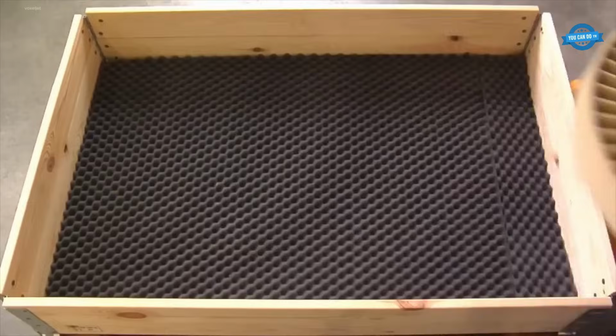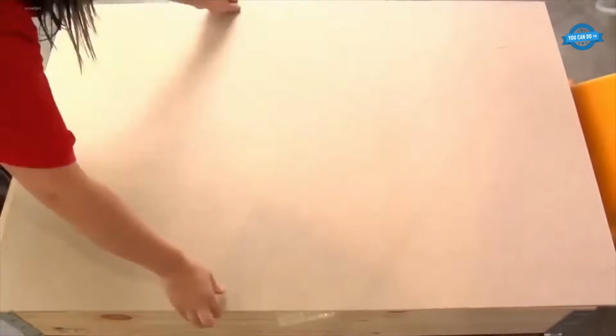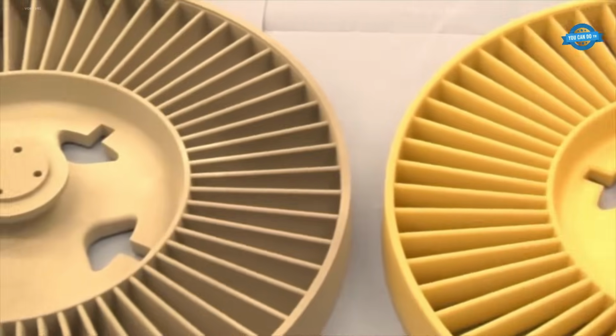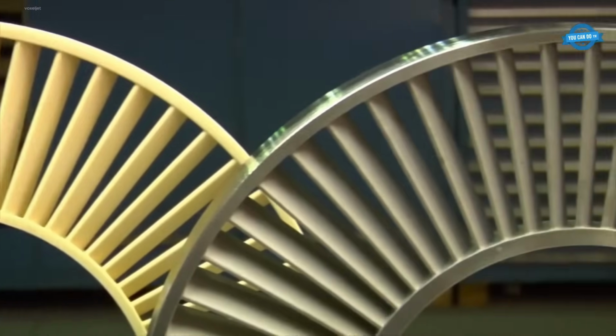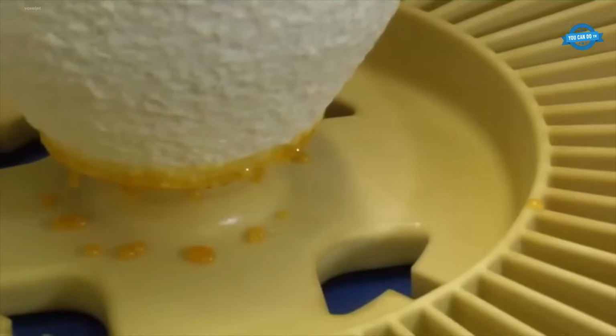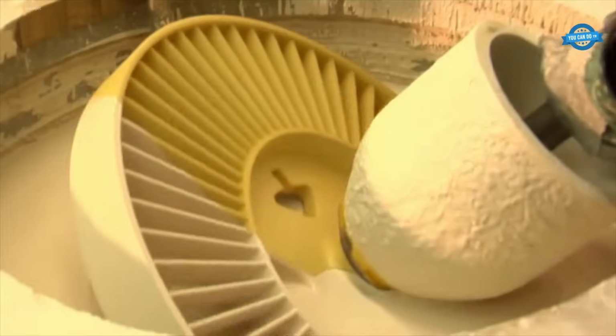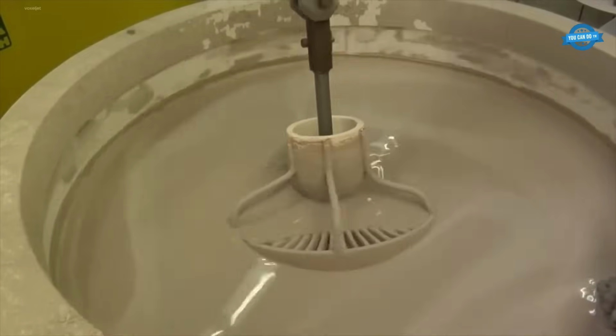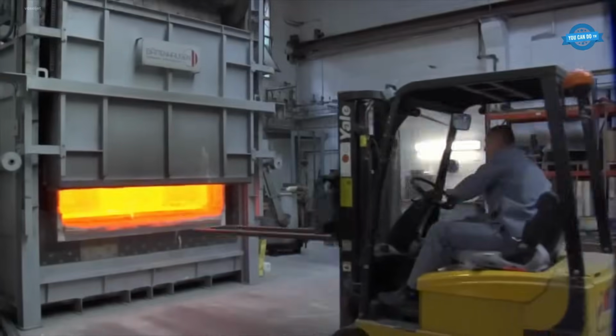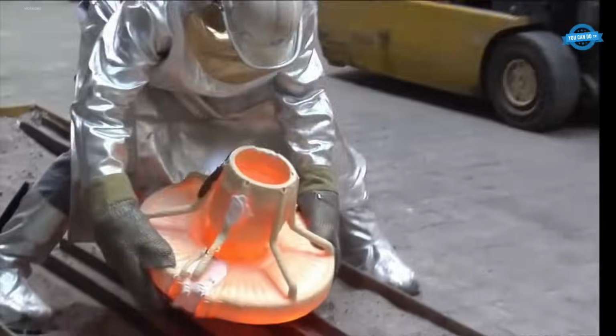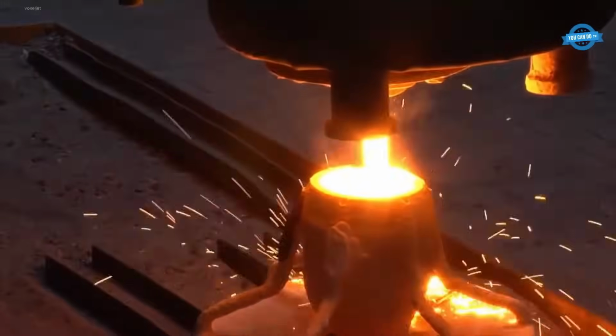After hardening, unprinted powder is removed, and the part is wax-dipped for smoothing. These printed models are processed like traditional wax patterns. Burnout leaves no residue, enabling clean casting with stainless steel at 1,600 degrees Celsius. The final parts undergo finishing, inspection, and testing, offering a fast, cost-effective alternative to conventional casting methods.